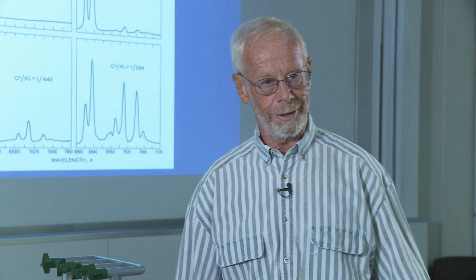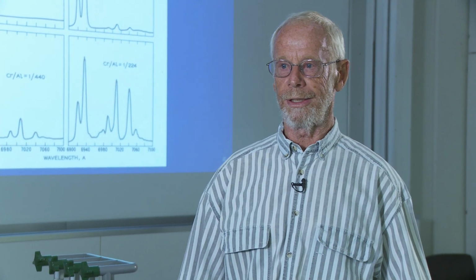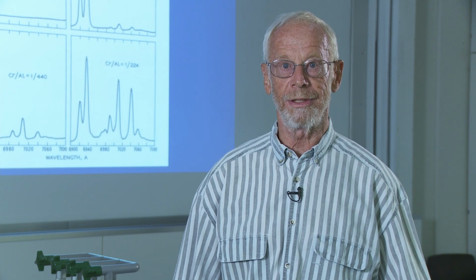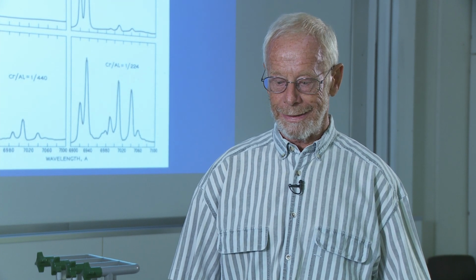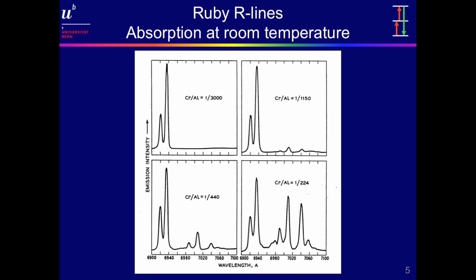And now I'm coming to the first scientific example, ruby. There are hundreds, maybe thousands of papers on the ruby R lines, the red lines around 700 nanometers. And here you see absorption spectra of rubies of different chromium concentration. The upper left panel shows the spectrum of a chromium single center in a slightly distorted octahedral coordination. With increasing chromium concentration, side bands are coming up on the low energy side, and these bands are due to chromium dimers and trimers.